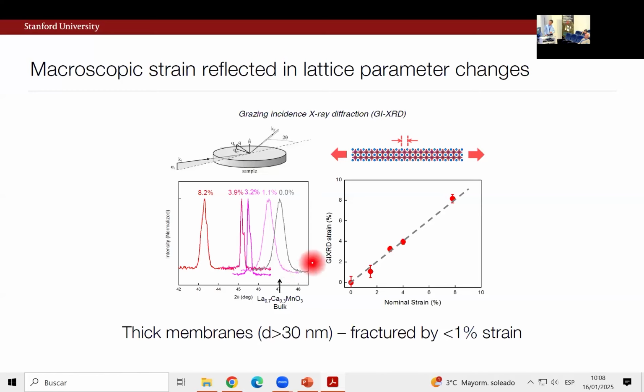So this is an example of this manganite membrane assembled, as I told you, at about 50, 80 degrees C. And this is probably one of the early, most dramatic examples that I can show you of having an enormous ability to elastically respond to an applied stress, right? So this is the lattice constants, and these are the visually identified nominal strain versus the stretching of the lattice constant.